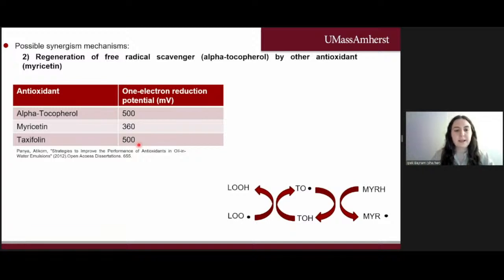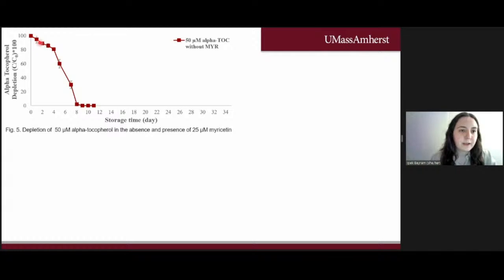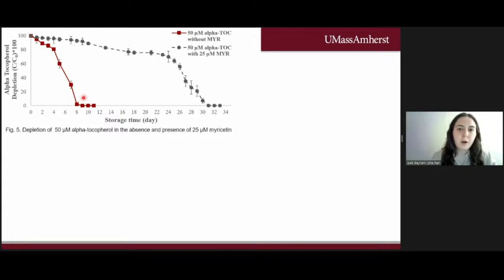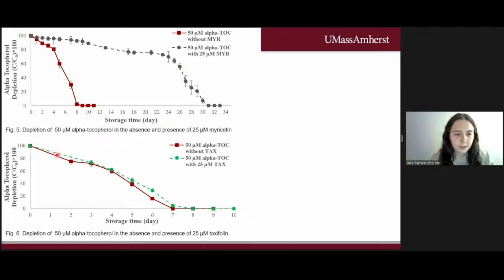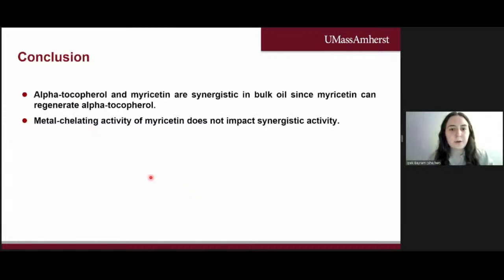To further support this, I analyzed the antioxidant degradation behavior throughout the storage study using HPLC. What I observed is that when tocopherol was alone, all tocopherol was gone after 8 days. But when we combine it with myricetin, the tocopherol survives for 31 days, which shows the regeneration of the tocopherol. But when we check the same result with taxifolin, we don't see any change in the behavior. So in conclusion, these two antioxidants are synergistic due to the regeneration of tocopherol, but not because of chelating ability. Thank you.